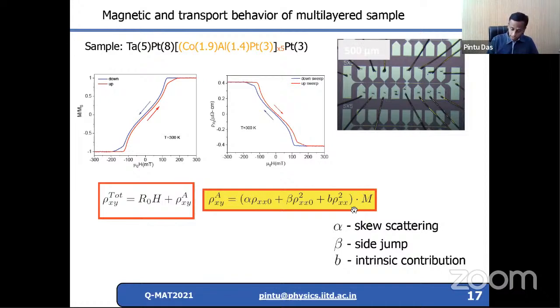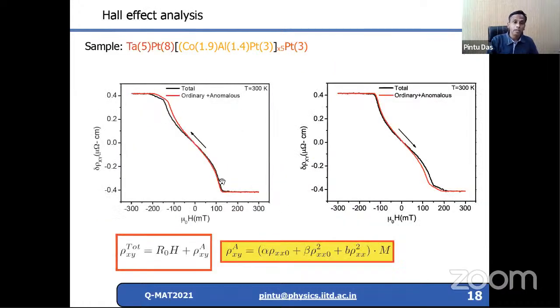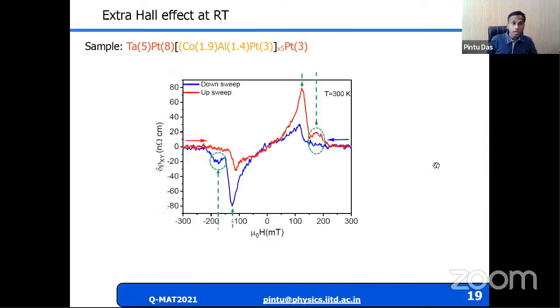So now using these parameters, we analyze this data, and we look at the total, the ordinary and anomalous Hall effect. We see that in the total Hall effect, there is an additional component. And this we systematically observe in both the upsweep and downsweep curve. Now, if we subtract the anomalous Hall effect from the total Hall effect, this additional component appears as a peak and a dip on either side of the zero field. That means when we are downsweeping the field, we see a small peak first, and then a dip on the other side, and this is repeated when we sweep the other way around. And this is very much reproducible.